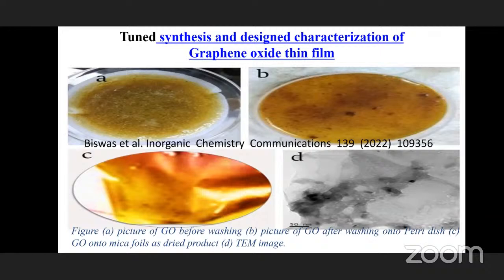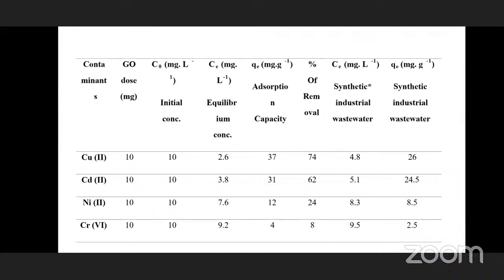Picture A is the raw graphene oxide before washing by ethanol, and picture B is after washing on the petri dish, and C is the dried product on mica foil. And picture D is the TEM image of the graphene oxide. We have applied this graphene oxide for removal of some heavy metal ions like copper, cadmium, nickel, chromium, etc., and we got a good result for the removal of heavy metal ions.